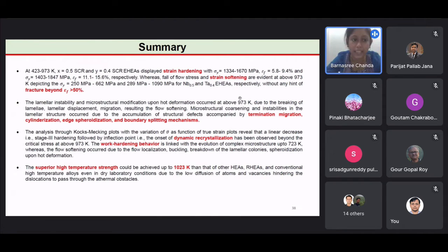From this, we can conclude that at intermediate temperature, strain hardening is dominating, and at higher temperature, a fall of stress occurs, and strain softening can be evident without any hint of fracture beyond 50%. And various kinds of lamellar instability can be seen after hot deformation, that is termination migration, cylindrization, edge spheroidization, and boundary splitting. Also, the Kocks-Mecking plot shows that dynamic recrystallization occurs on the onset of the critical stress, and the work hardening behavior is linked with the complex microstructure of the eutectic high-entropy alloys. Superior high temperature strength can be seen when we compare the eutectic high-entropy alloys with the other high-entropy alloys, refractory high-entropy alloys, and the conventional high-entropy alloys.